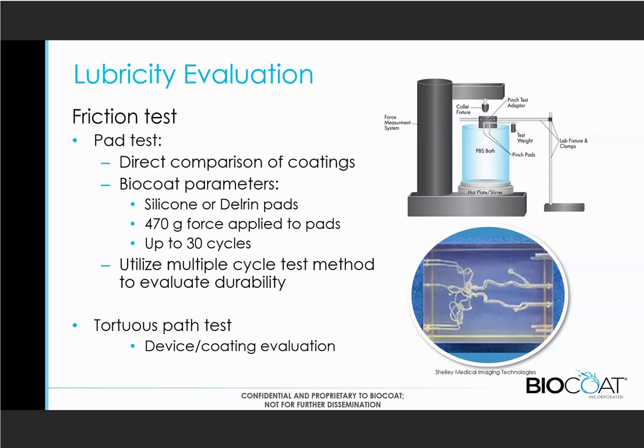For us, we're using 470 grams of force with either a silicone rubber or, in more aggressive cases, a Delrin pad. We squeeze that together and then pull the sample up between those pads, measuring the force that it takes to slide up there. We'll typically do up to 30 cycles, and actually can go up and down through there and measure that force.